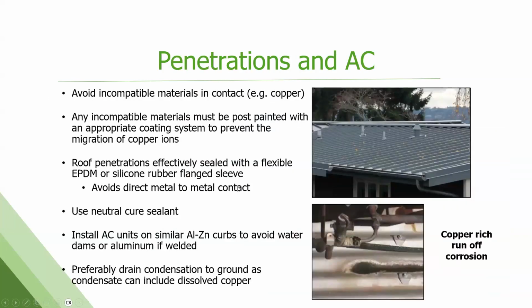So again, avoid copper. This is an example of copper dripping, running off onto a bare Galvalume roof. Really bad, kind of black, unsightly corrosion that occurs. Incompatible materials can be painted, right? So it's not direct contact. If the stainless steel is coated or painted with something, then it should be okay. The copper, if the copper is painted, so there's not direct contact between the copper and the bare Zincalume or Galvalume product, should be okay.